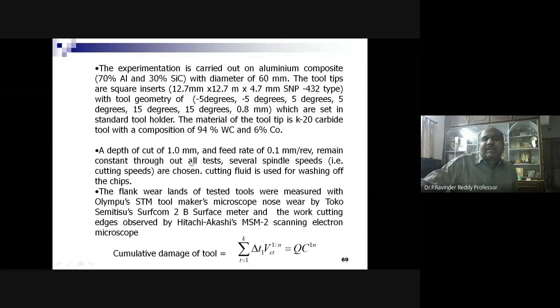A depth of cut of 1 mm and a feed rate of 0.1 mm per revolution remain constant through all the tests. Several spindle speeds are selected. Cutting fluid is used for washing of the chips. The flank wear lengths of tested tools were measured with an Olympus STM tool maker's microscope. The nose wear by Toko Semitisu's Surfcom 2B Surface meter, and the worn cutting edges were obtained by a Hitachi Akashi MSM2 scanning electron microscope.